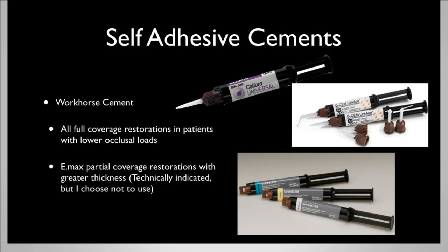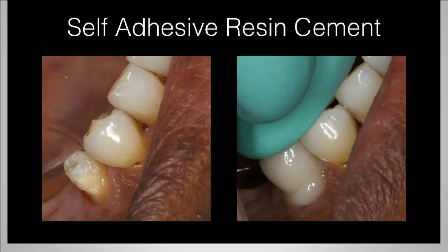So if I'm cementing a zirconia crown today, or maybe an E.max or lithium silicate restoration that's thicker, I'm comfortable using these cements, but I do not use them for partial coverage. These cements have improved quite a bit over the years. If you take a look at this clinical slide, in this case, this lower right second bicuspid was a tall preparation. I had 1.5 millimeters in thickness. It was a strong glass-based restoration. We conventionally cemented this. So I used a self-adhesive resin cement, and that's what we utilized to cement this in place. And really had no issues with it because it was tall, naturally retentive, and plenty of thickness.